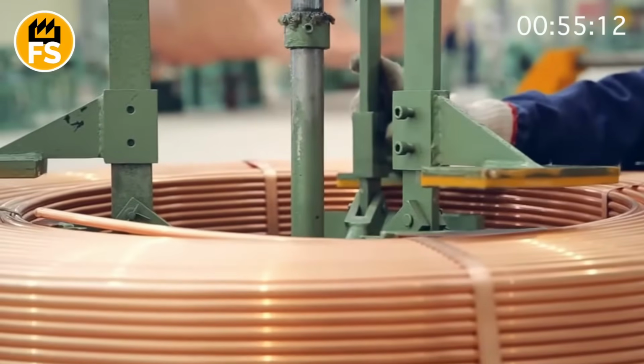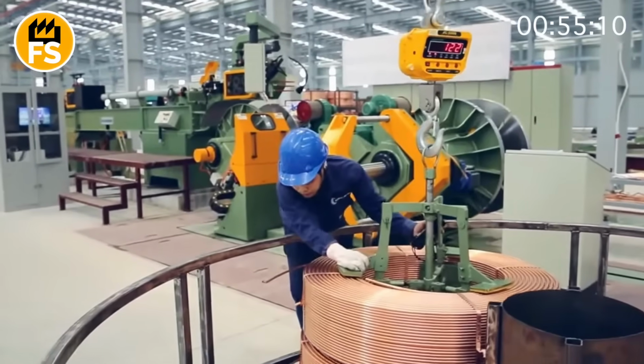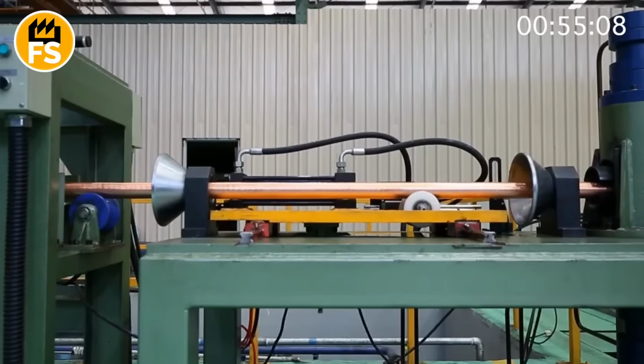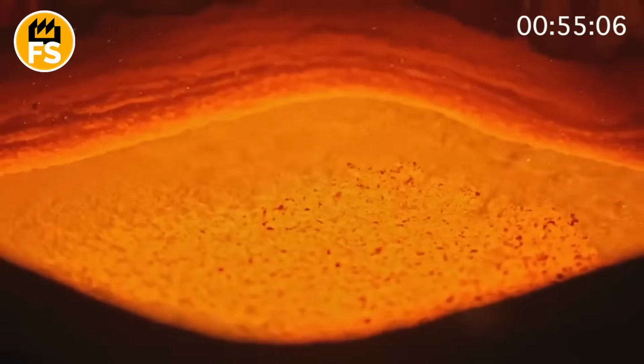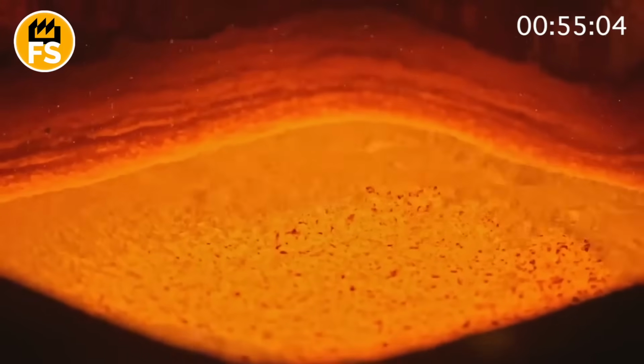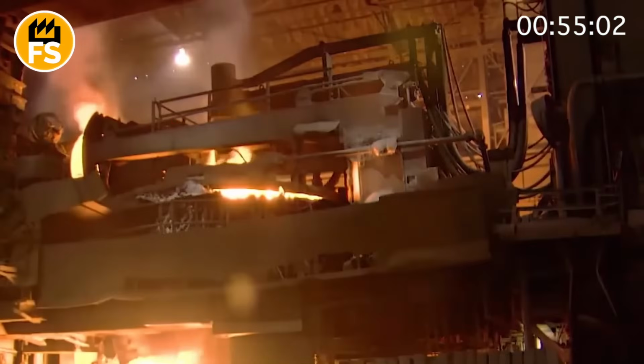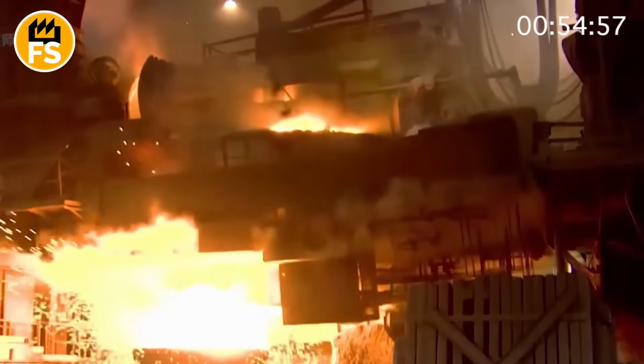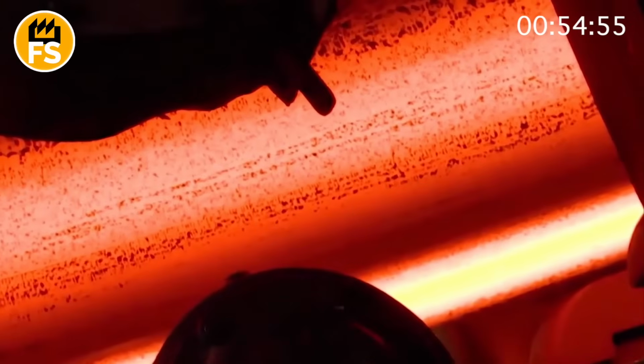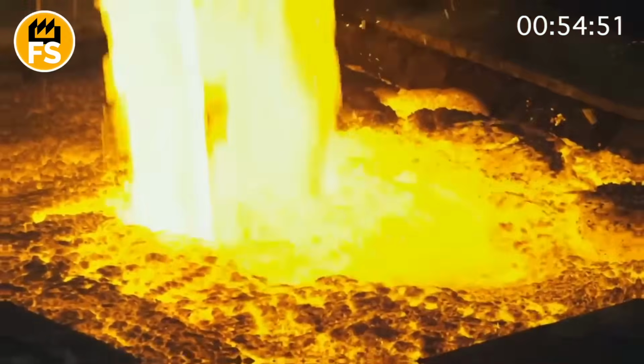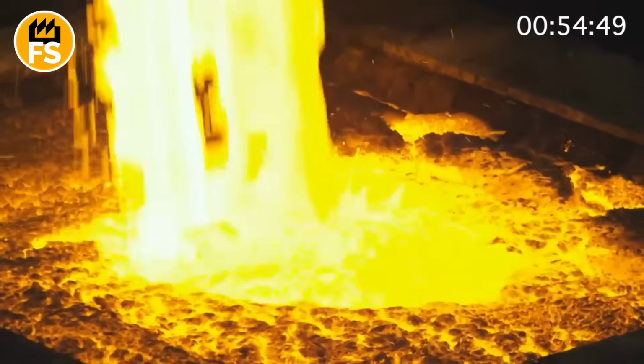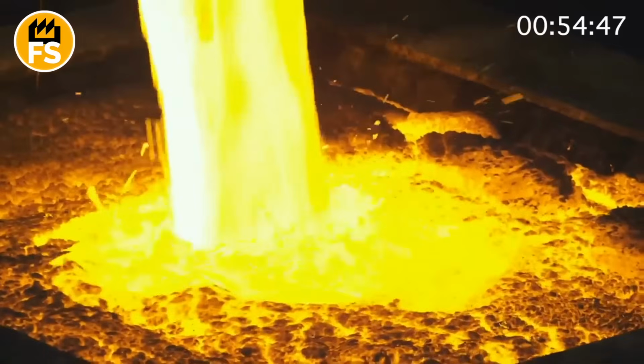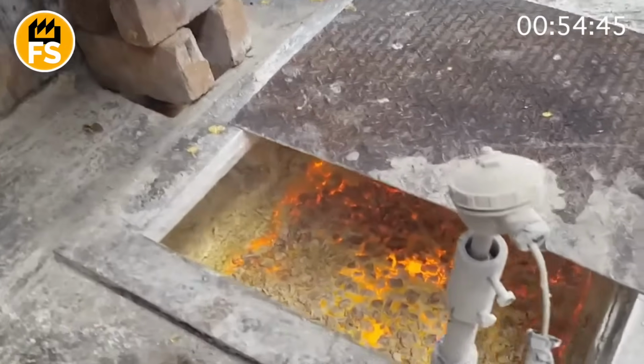Everything that has just been gathered, copper cathodes, ingots, zinc bars, tin granules, is loaded into furnaces that know no mercy. These are either induction furnaces, where the metal is heated by an electromagnetic field, or gas-fired crucibles, where the flame can be heard even through thick walls. The temperatures here are hellish. Brass melts at 1700 degrees Fahrenheit. Bronze requires even more, up to 1910 degrees.